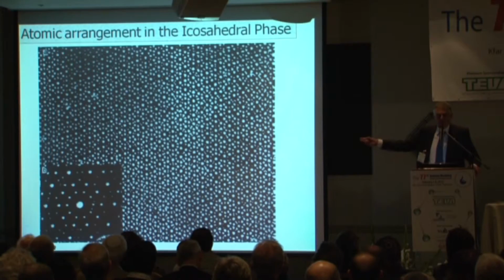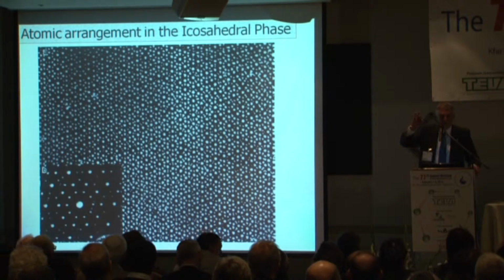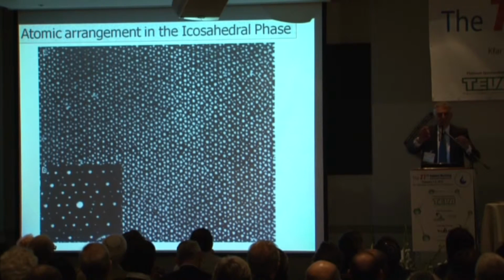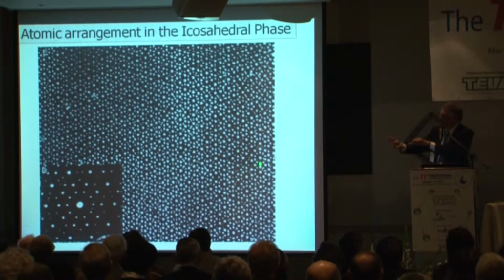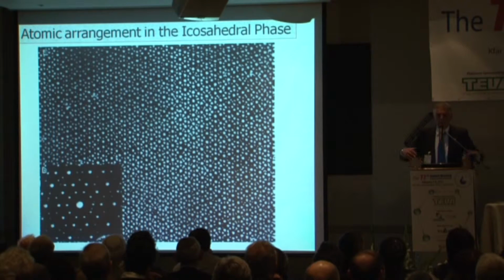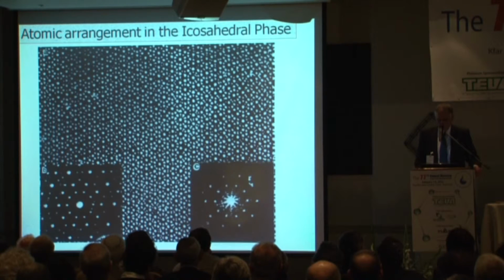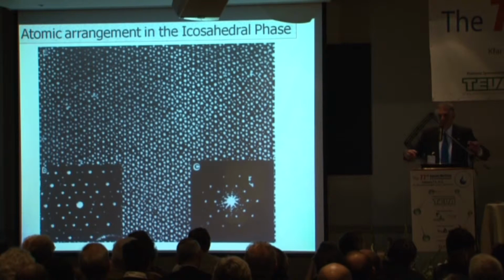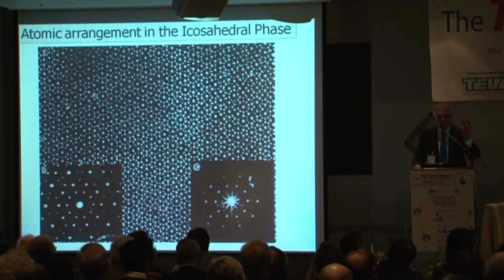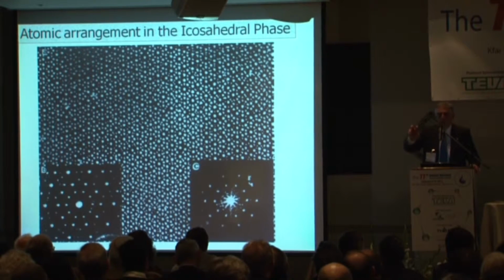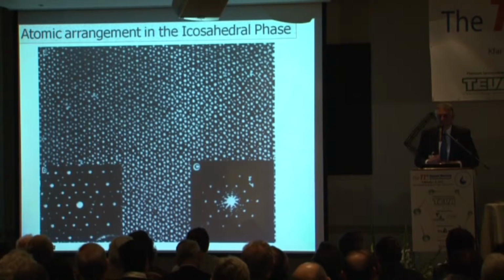They took this slide, put it on a transparency, but very, very small. Remember slides? Those days we showed slides. And shone a laser beam through the slide, like that. Very simple, okay? And formed an optical diffraction pattern. And that optical diffraction pattern should look exactly like the electron diffraction pattern, because they both are Fourier transforms from the same image. Here it's the image in the electron microscope, and here is the optical image using a laser beam. And they should look the same.